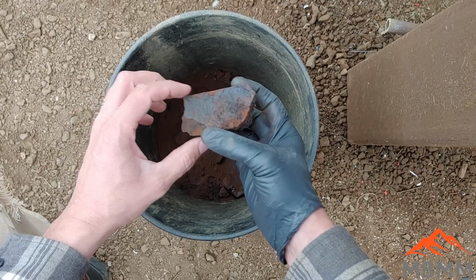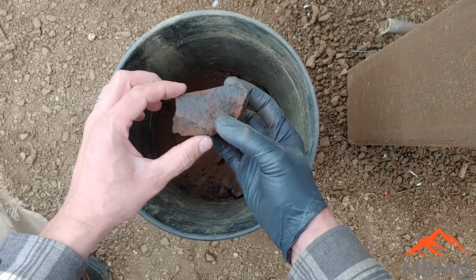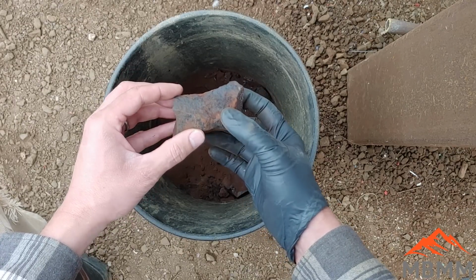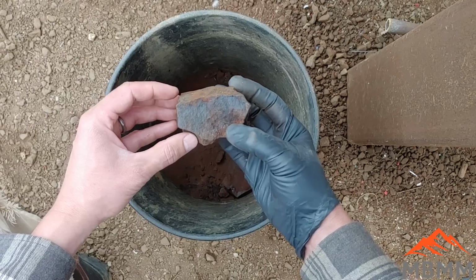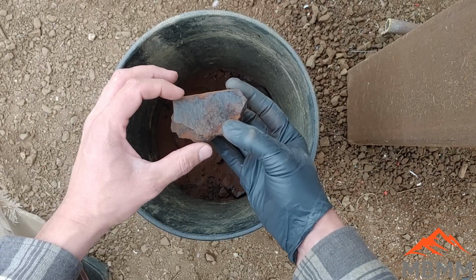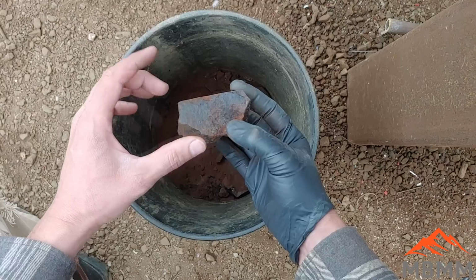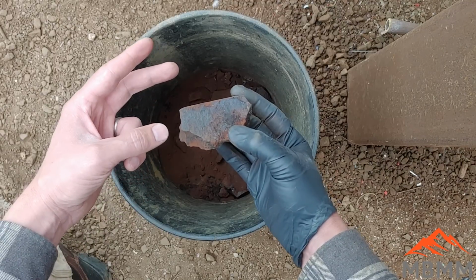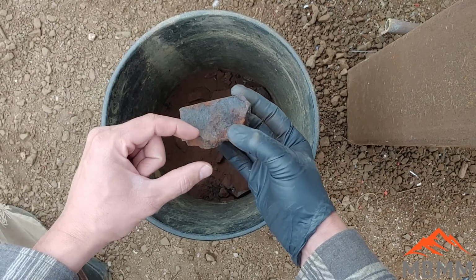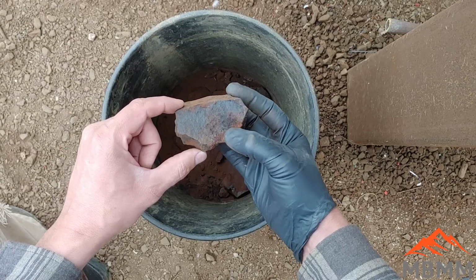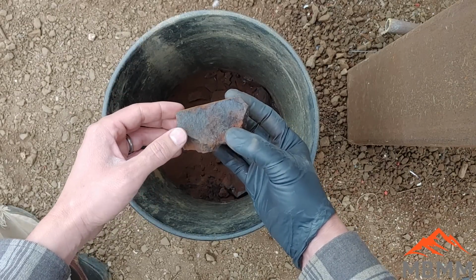And this is bad because even though it's mostly sulfides, some of your precious metals will be contained in this matte layer. And so the goal of every smelt or assay is to get just two phases, the slag layer and then your collector metal. If you have a matte phase, you kind of want to reevaluate what you did and try and get rid of this matte phase.